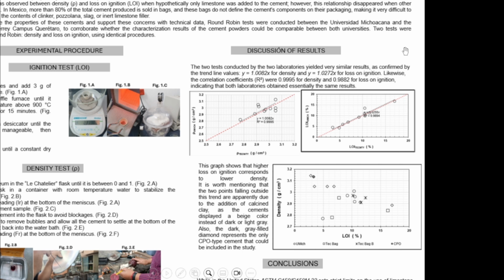Discussion of results. The two tests conducted by the two laboratories yielded very similar results, as confirmed by the trendline values y = 1.0082x for density and y = 1.0272x for loss on ignition. Likewise, the correlation coefficients, R squared, were 0.9995 for density and 0.9882 for loss on ignition, indicating that both laboratories obtained essentially the same results.